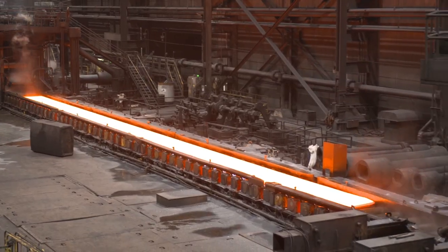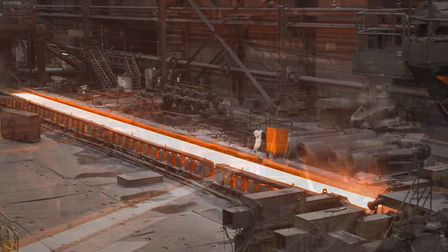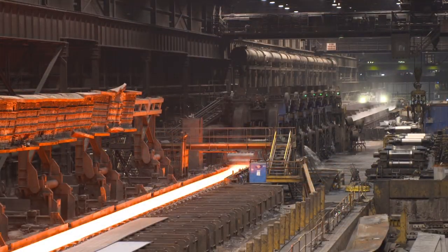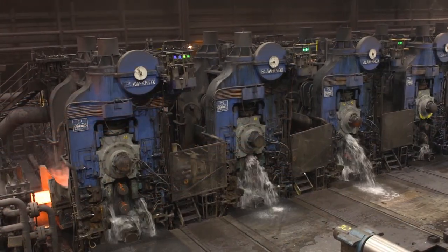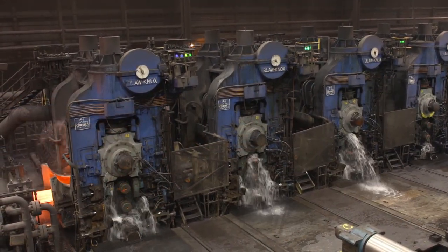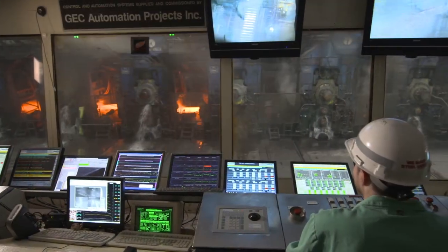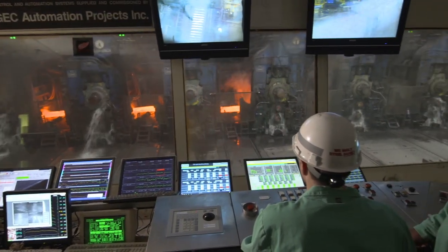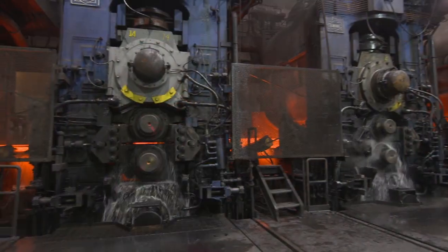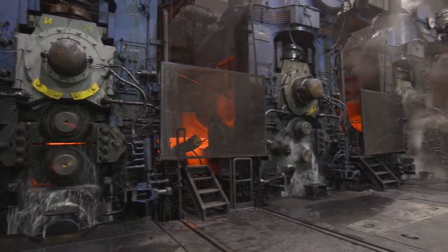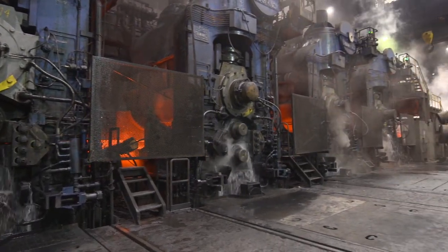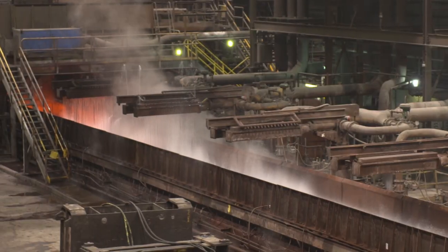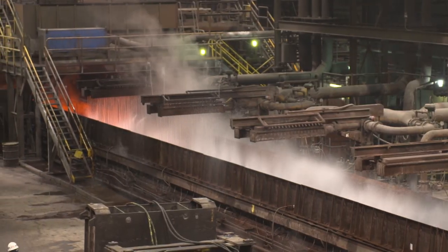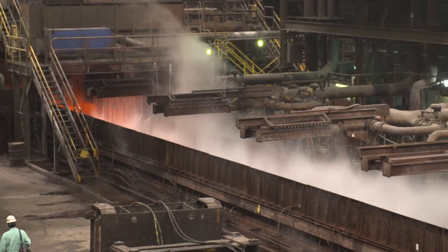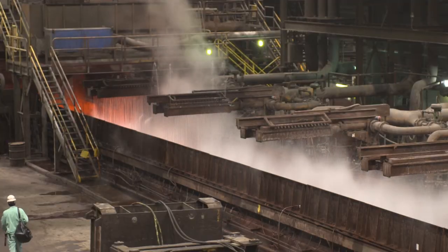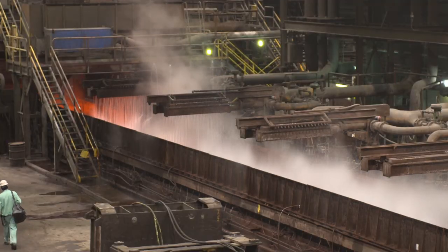As the red-hot slab leaves the roughing mill, it enters the 7-stand finishing mill and is reduced further to the ordered gauge, as thin as 0.070 inches. A slab 33.5 feet long can become a coil of steel about 4,100 feet long in a matter of minutes. The ribbon of steel continues over a runout table, where the steel is cooled with water sprays programmed to create the specific physical requirements of each order.